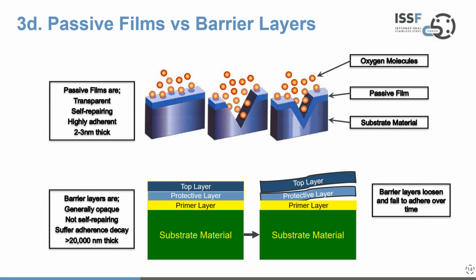So let's have a simple look at passive films versus barrier layers. The top diagram set shows the passive film arrangement. If you look at the left hand of the three diagrams in the top half, there you have the substrate material at the bottom, the passive film sitting on top, and oxygen molecules hanging around as they do in the atmosphere. And if you take a trusty instrument, an axe or something similar, and inflict a nasty groove in the material, you've clearly destroyed the passive film momentarily.